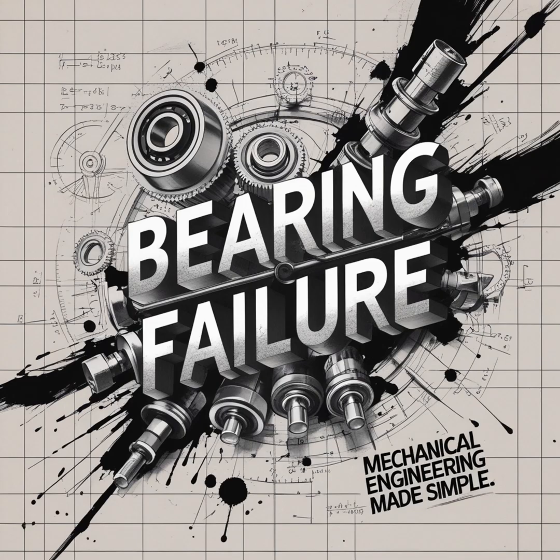Exactly. What about a high-pitched sound, a scraping or a sliding sound? That's often skidding. It happens when the rolling elements are sliding instead of rolling. Maybe the bearing doesn't have enough load on it, or the lubricant you picked is just too stiff for the operating temperature. And then there's the really modern failure mode we see more and more.